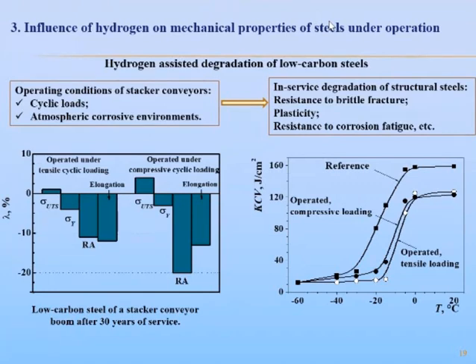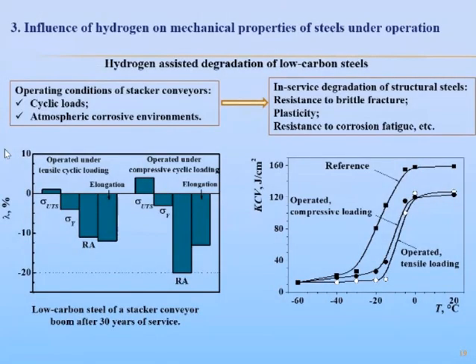So the presented data show relative changes in mechanical properties of the carbon steel in different states. A minor change in strength characteristics of operated steel compared with the reference steel was observed. Reduction in area and elongation at fracture decreased as a result of long-term operation. And as can be seen from these results, both tensile and compressive cyclic loading and the operation lead to plasticity deterioration.